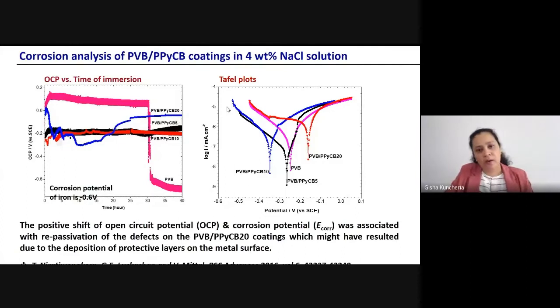Coming to the coatings containing conducting polymer, especially the 20% conducting polymer, here also the potential is slowly decreasing. But after some point, you can see the potential moving up and retaining its initial potential. This is the behavior of self-healing coatings. When this coating was immersed in the 4 weight percent sodium chloride solution, some defects or water ingress happened on the coating. But the self-healing coating healed those defects and retained its protection to its initial value. This is the self-healing coating.